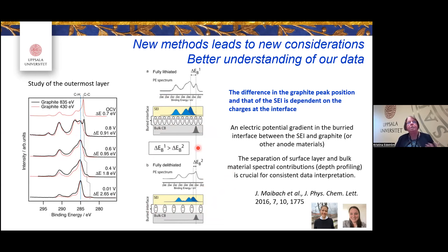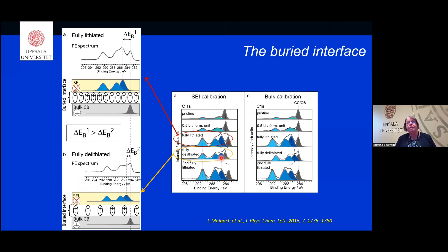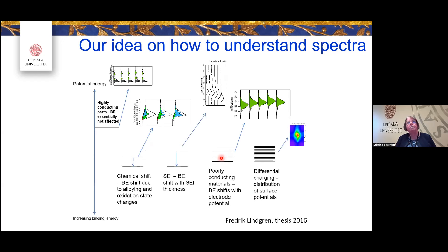This analysis can also be used to quantify how much lithium builds up in the interface, showing that even with low cycling you get a little buildup. You can look at different depths and see how binding energies shift. This is important for how we use and interpret results — we are perhaps still a bit old-fashioned in how we handle XPS data. If you have a highly conducting part like graphite, binding energies are essentially unaffected; for a less conducting layer like the SEI, you get chemical shifts; for poorly conducting materials, the binding energy shifts with electric potential.